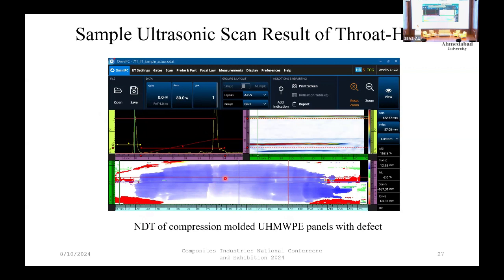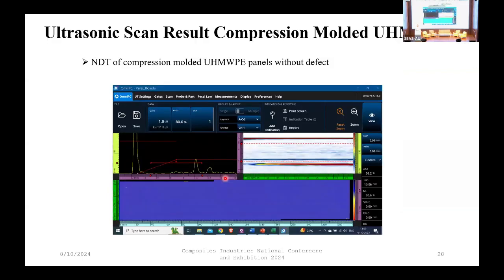It means lack of pressure or incomplete consolidation of the material. Had it been the perfect one, there would be no reds and whites; reds mean defect and whites mean inappropriate consolidation. If it is a perfectly consolidated material, then the outcome of a C scan would be a completely blue screen, something like this. Though it has a couple of defects, they might not be visible. Over here I can see something just above my cursor. These types of very fine defects are acceptable, but not the previous screen.